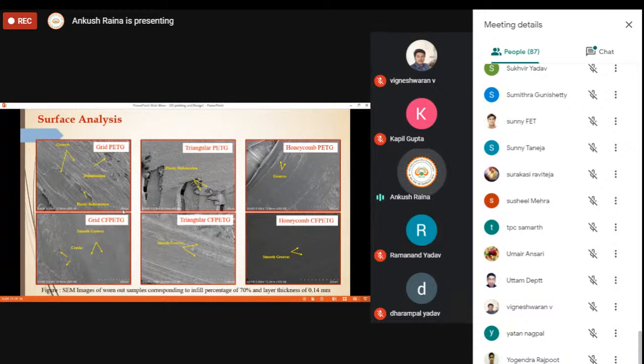This SEM has been carried out at 200 micrometers. So if you take into consideration the triangular PETG, here also you can see there is a lot of deformation which has taken place. Whereas if you talk about carbon reinforced PETG, you can see again the surface is smooth. A similar observation has also been made with the honeycomb CF PETG. So in short, what we can say is that carbon reinforced PETG has the capability to reduce the frictional characteristics, to reduce the wear characteristics, and ultimately to give the smooth surface finish, which is ultimately the requirement of any sliding component from the tribological point of view.